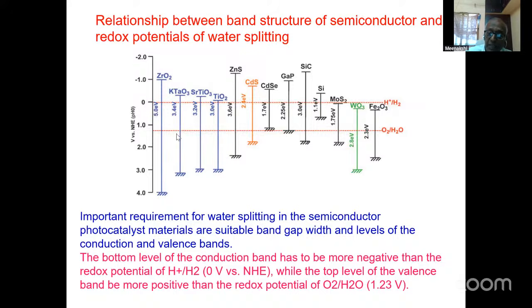At the same time, when the valence band potential is above 1.23 electron volt, the catalyst is capable of splitting the water into oxygen. Here you can see tungsten oxide and iron oxide are not capable of reducing the H plus ion to hydrogen. They are capable of only splitting the water into oxygen. So the band potential levels are more important for splitting the water. Not only the band gap energy decides, but also the band potentials decide the splitting of the water.